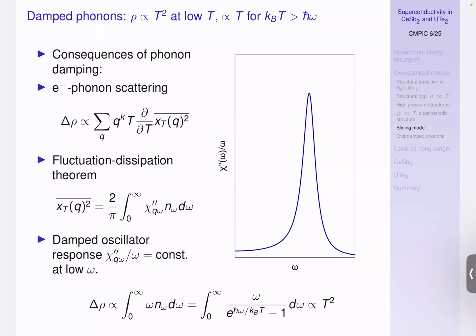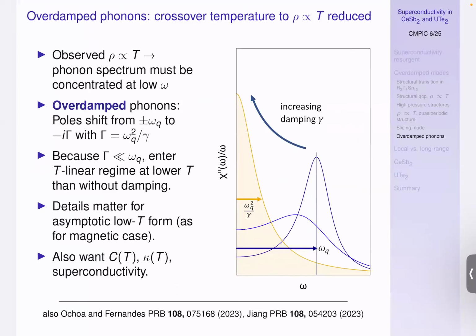But we don't see linear in T. So linear in T, okay, we would get if the phonons become overdamped, which is what I explained earlier, so that your temperature scale doesn't lie in the tail of an underdamped response, but lies above the peak of an overdamped response. And then you would get linear in T. But the question is, would that even persist as the temperature now approaches T equals 0?